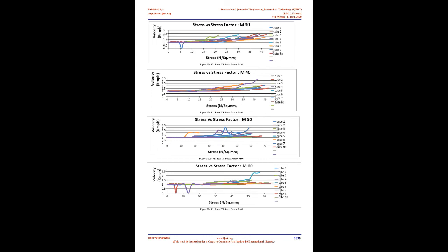In IS Code Clause 6.4, IS 13311 Part 1 1992, Non-destructive testing of concrete, they have mentioned that it causes a negligible effect on the velocity of the ultrasonic pulse. But as we observed above, they significantly affect the velocity. Hence, to minimize this error, we are introducing a new methodology to find the correct velocity of the ultrasonic pulse.